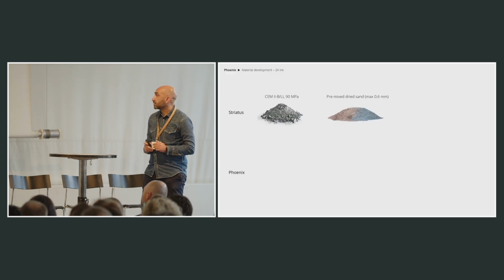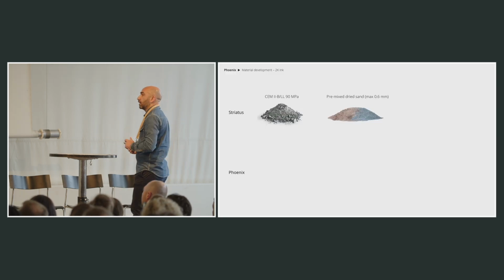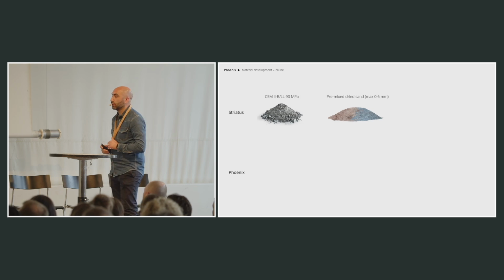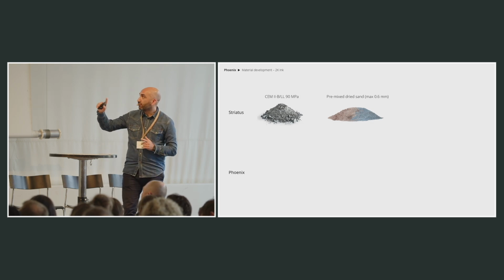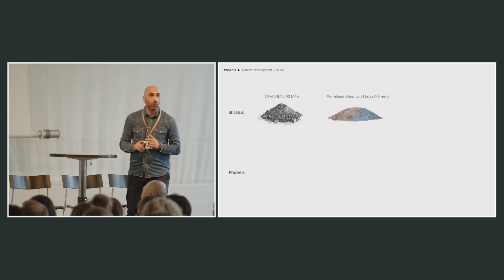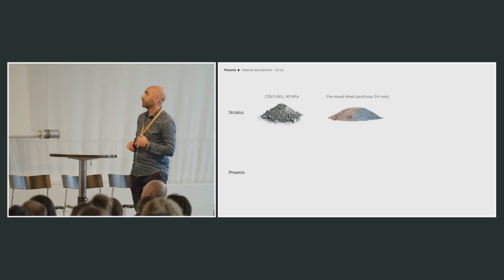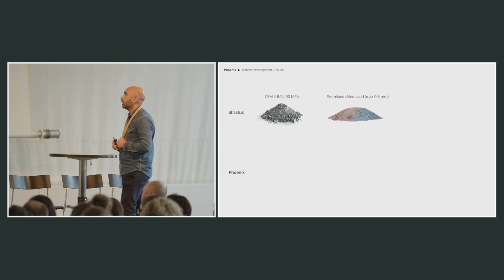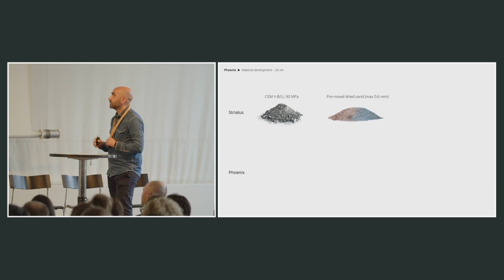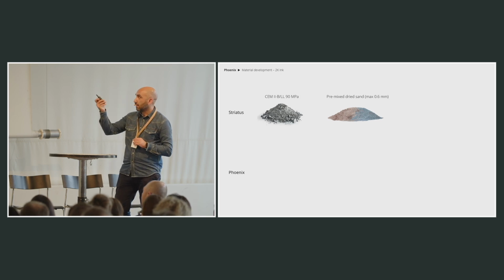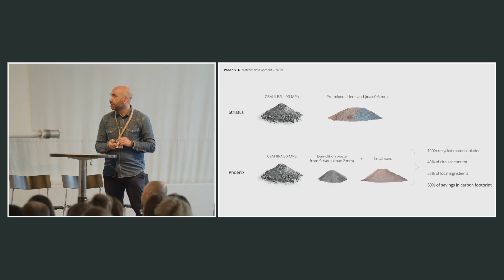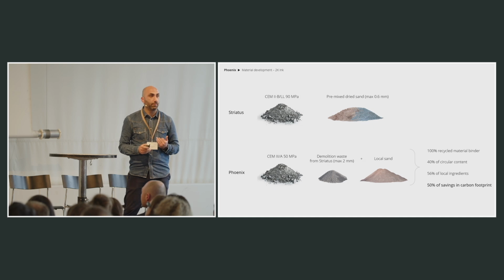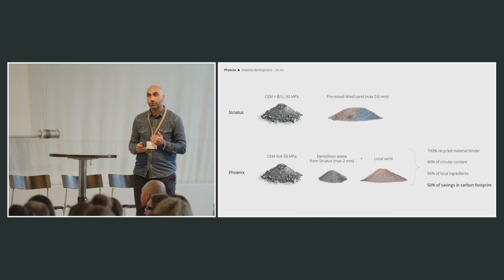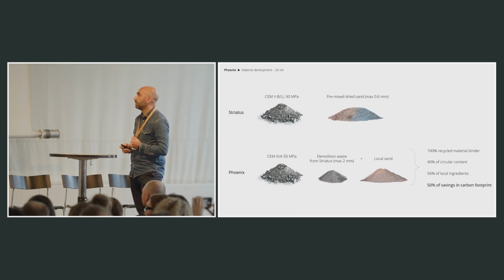But not only that, so the development between Striatus and Phoenix concerned also going from a 90 megapascal concrete, so a high-strength concrete with the maximum diameter of aggregates about 0.6 millimeters, CEM I, to CEM III concrete with the 50 megapascal, so we could reduce a lot also the environmental impact of the mix.